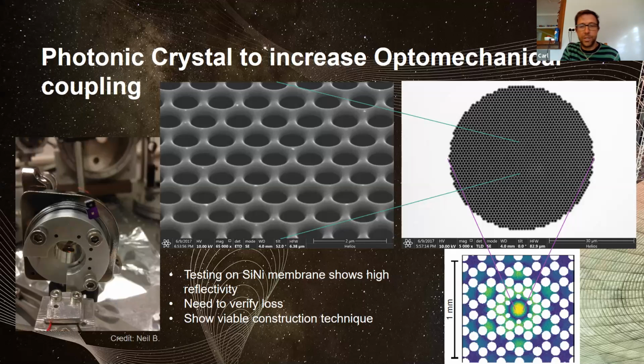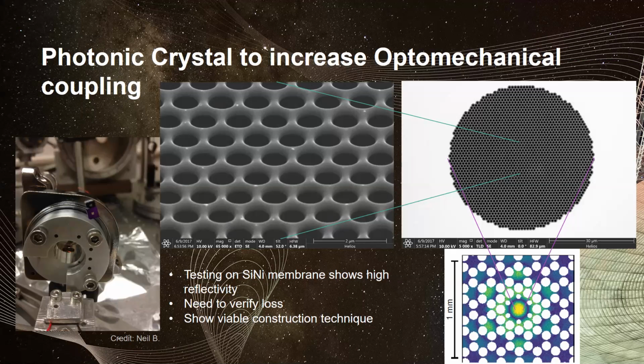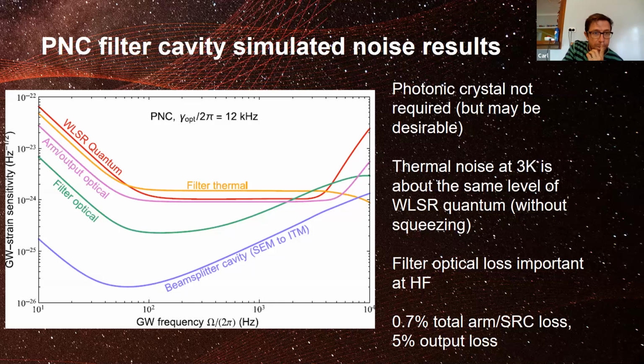Due to their incredibly high Q, they're adequate for our needs. But we are also investigating ways to improve the optomechanical coupling. There have been some experiments punching a photonic crystal into the defect in the center of the defect mode of the phononic crystal to increase the reflectivity. We still need to verify loss and show viable construction techniques. One minute. Okay, I better speed along.